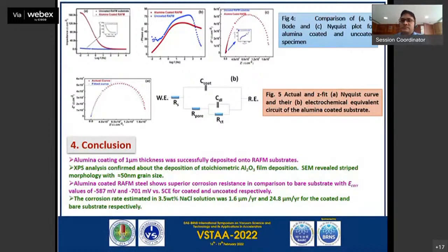So 1 micron is the thickness of the film. Yes, sir. And do you know the uniformity? I mean, plus minus something. Uniformity, I haven't checked, sir, because for measuring the thickness, we mask the substrate and take 5 to 10 readings across the masking. So we got approximately 1.05 micron coating for the 8 to 10 readings.